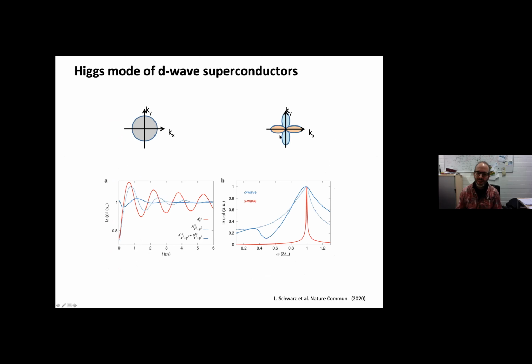And as I said in the beginning already, the first thing we have to take into account is this strong damping, where in an S-wave superconductor, we have these long-lived oscillations in the system. However, in a D-wave system now, you see already these modes get really, really broad already in a theoretical simulation of the system. And in addition, additional modes may show up due to these different symmetry channels that we can excite in this material.